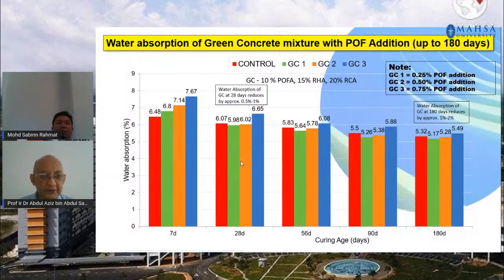And this is the water absorption of green concrete up to 180 days. Again, as you can see, the tendency for the material to absorb water is still there, but it seems to be reducing as the number of days increases. By 180 days, you have less water absorption in your material for all types of mix.